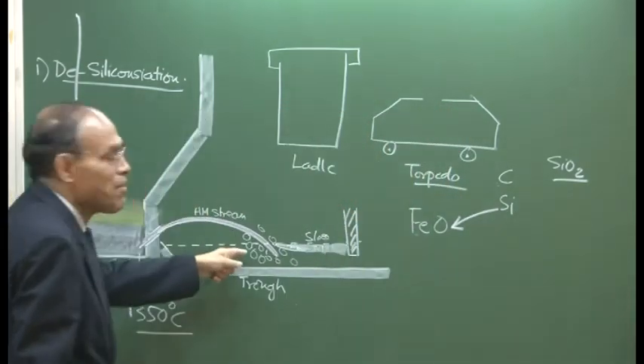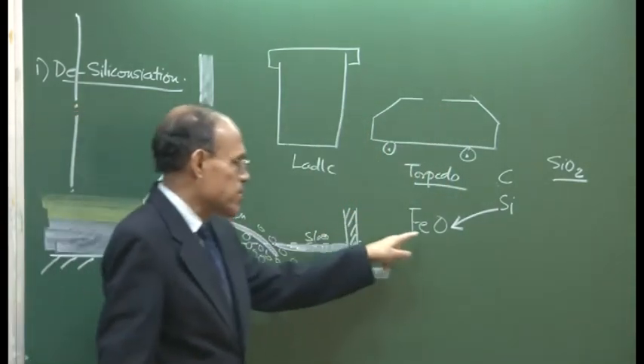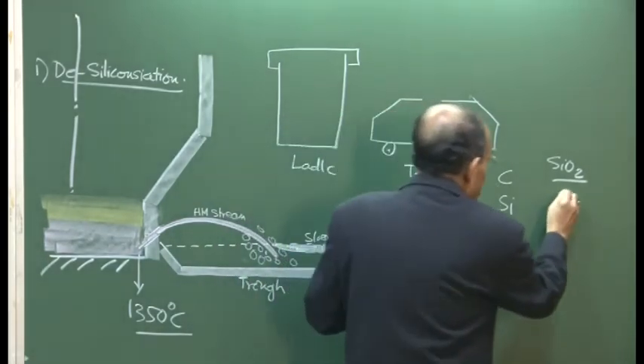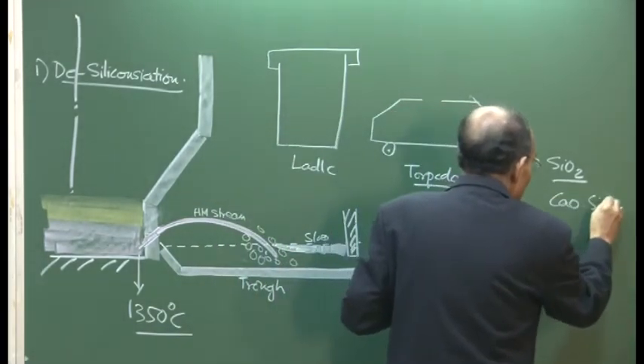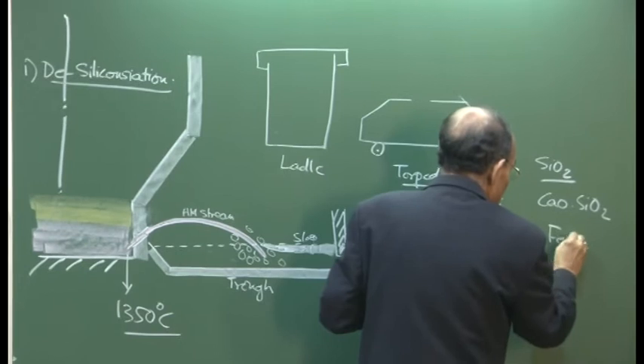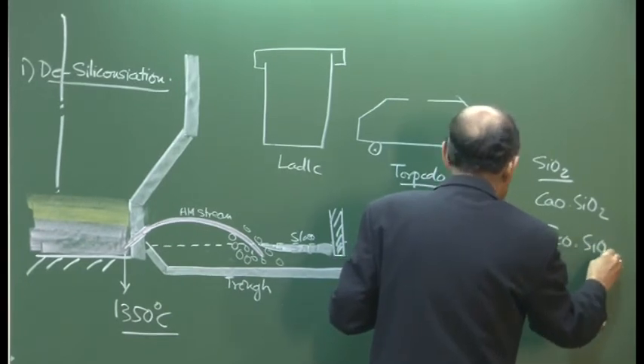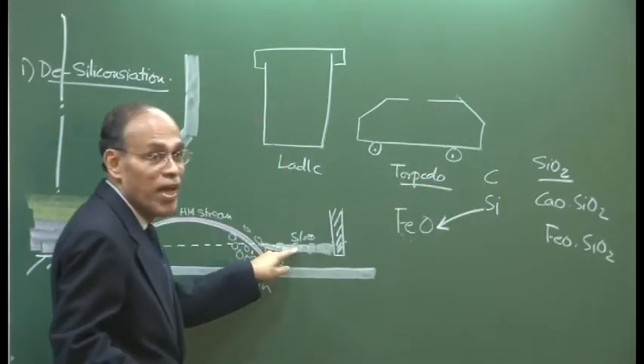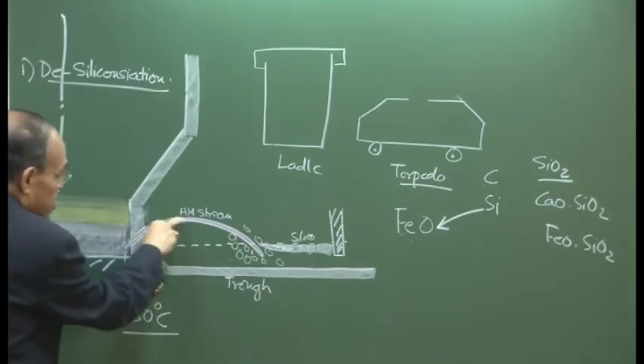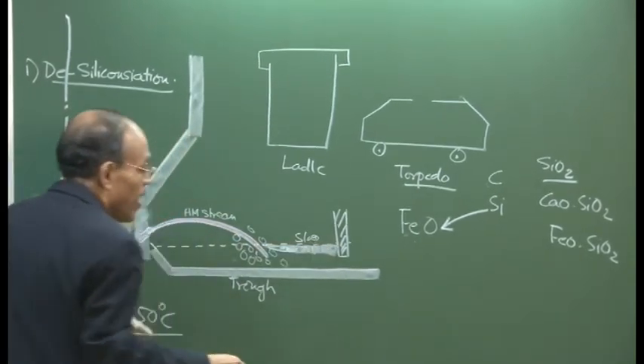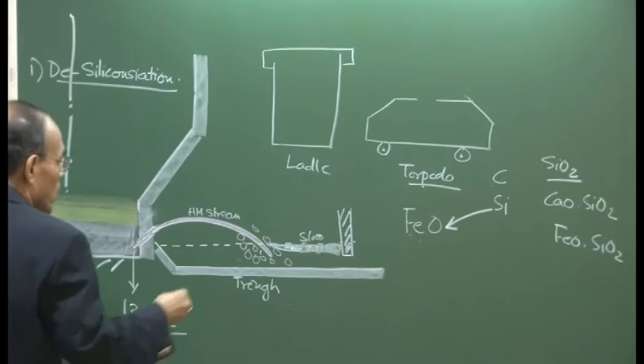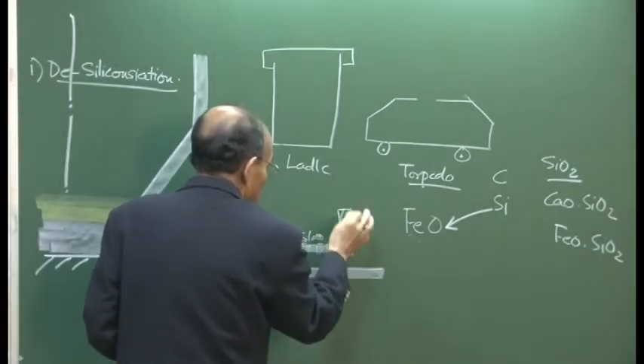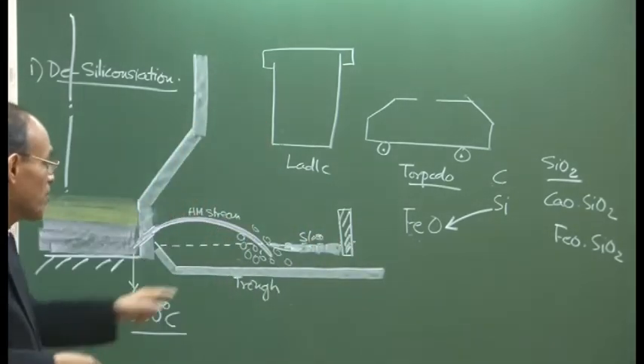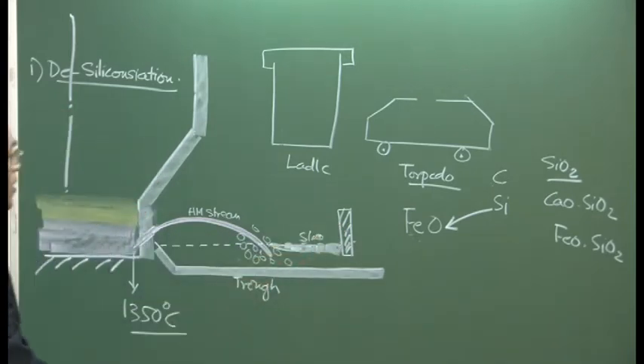You can also add lime powder here to fix this silica, and then calcium silicate slag will form, or alternatively FeO-SiO2 can also form. This slag, being lighter, will float up and may be mixed with the blast furnace slags should the slag be carried over here, and it can be skimmed off or rerouted in a favorable direction using the slag skimmer, which is this particular part in the whole system.